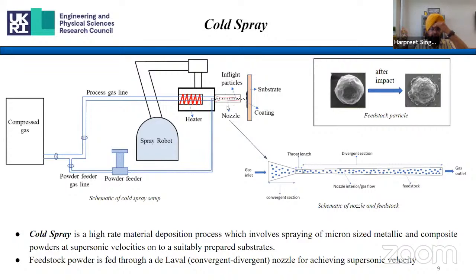So this nozzle is fed with our working gas, which is usually nitrogen or helium or sometimes air as well. And that gas is basically accelerated through this nozzle to supersonic velocities. And in the meantime, we also introduce our powder so that it gets accelerated through momentum transfer from the gas to the particles, and particles can achieve the desired velocities to get deposited on the surface. How they are getting deposited, I'll give you some hint, although my previous speaker has already talked about it slightly. So there are different types of adhesive mechanisms which are working here.